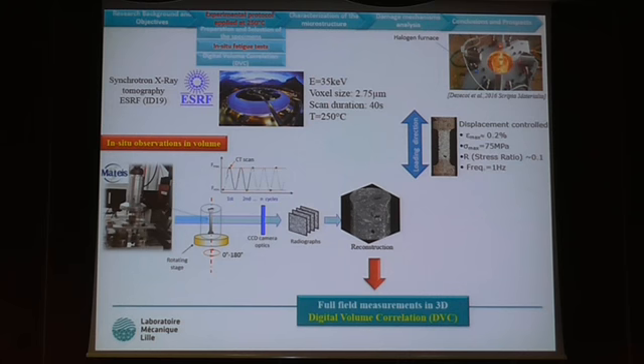The in situ fatigue tests were performed in the synchrotron ESRF at Grenoble in France. For that, we use a voxel size of 2.75 micrometer, and the scan lasts about 40 seconds. Here, it's the furnace. Furnace is composed by 4 halogen lamps. And this furnace is around the fatigue machine here. If you see the in situ observation details, you take an image at the minimum load and at the maximum load, then we perform some cycles and so on. After that we can have the reconstruction of the volume, and from that we can compute full field measurement in 3D.